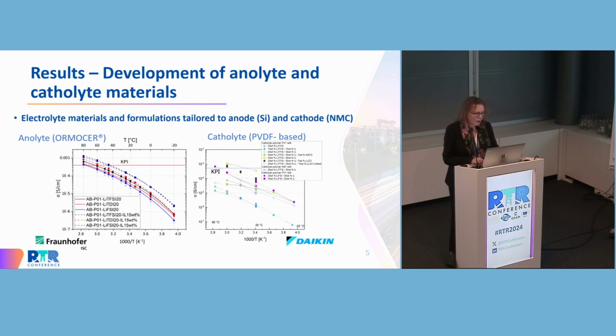For the anolyte, we have selected and tested different types of lithium salt: LiTFSI, LiTDI, and LiFSI. And we have also added some plasticizer in order to increase the conductivity. The plasticizer is ionic liquid. It is used in a content of 15% weight that allows to keep the solid aspect of the materials.